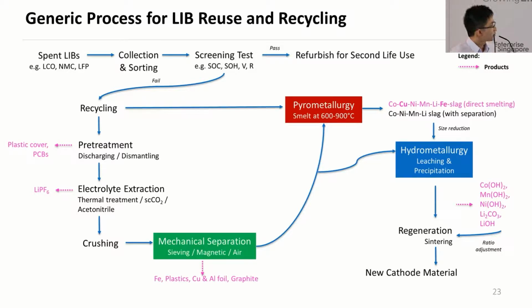While for the next path, you will go through a pretreatment process such as discharging, dismantling, electrolyte extraction, and they are size reduced by crushing, and then subjected to mechanical separation. This separation process is important to separate out impurities such as iron, plastics, copper, and aluminum foils, so that you will obtain a purer slag after the pyrometallurgy process.